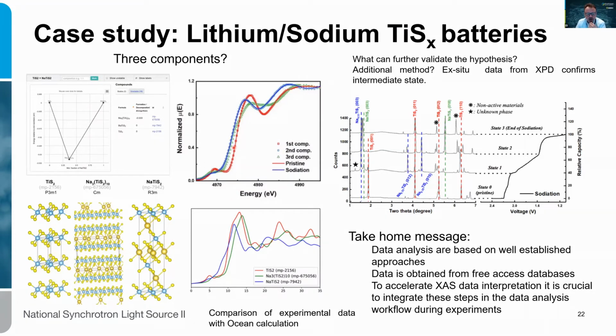And the good thing is now we can design the next level of experiments, say to go in a multimodal direction, take diffraction, for instance, and we can look for a specific peak belonging to this phase, and indeed we identify this in this supporting experiment. So this data analysis is a very well-known technique which is only in the last decade recognized in the EXAFS world, but it's really powerful, especially when you can do it on the fly, when the data is still hot.